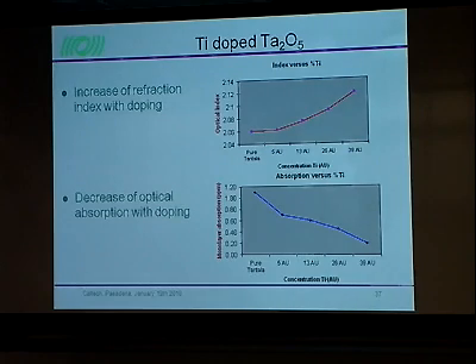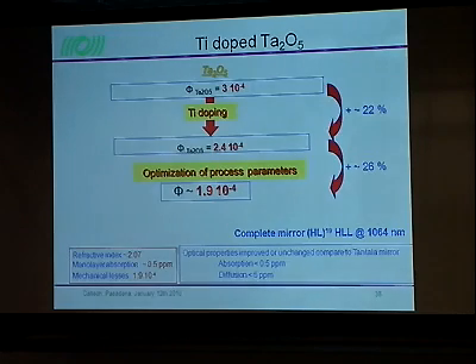So everything goes in the right direction. The index of refraction increases, the optical absorption decreases, the mechanical losses decrease. It's like dreaming, and it's the best material that we were able to synthesize. By doing some optimization of the process parameters, we were able to reduce the losses in the range of 2 × 10^-4, and in some cases even below 2 × 10^-4. And the absorption, as I said, is in the range of 0.5 ppm. This was done both on monolayers and on full mirrors.